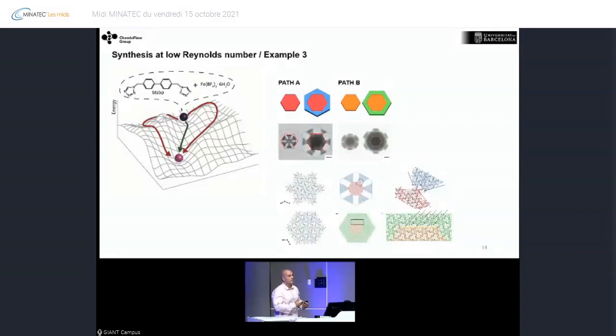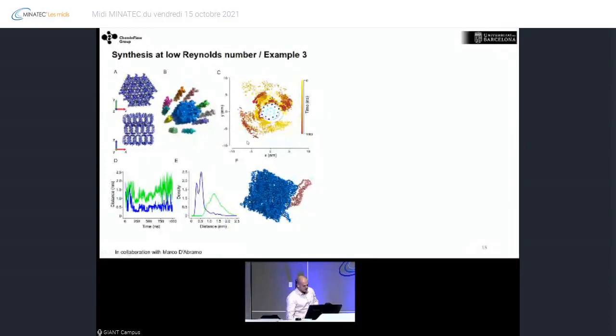So we needed to further corroborate the results by doing numerical simulations, and this is what we did here. What you see is full-atom molecular dynamics simulations, where we have 10 strands of this coordination polymer, and in the center we generate a cluster of these strands made of up to 19 strands, okay? We position these 10 strands 1 nanometer away from the central one, so that we are completely sure that the system is unbiased. The blue dots here are the growth from the vertex, whereas the green are from the face.